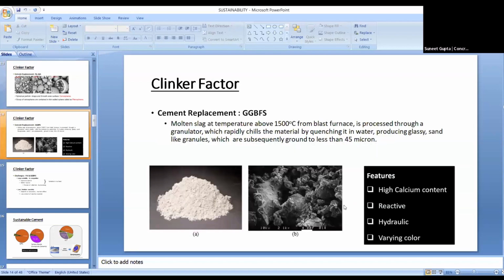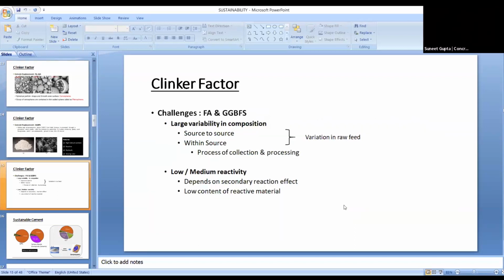Similarly, GGBS, what we call ground granulated blast furnace slag, which we get from the steel industry. Here also it has high calcium oxide levels, and that's why the replacement level of clinker is more in slag than in fly ash. So wherever slag is used, we can replace the clinker, and hence the usage of limestone can be reduced by up to 50%.